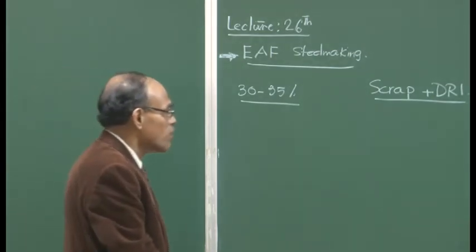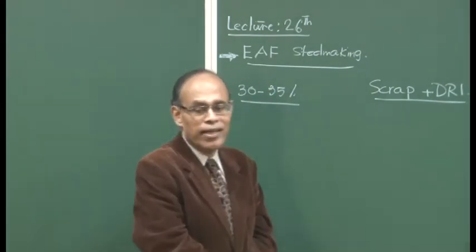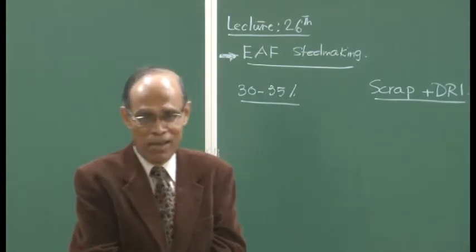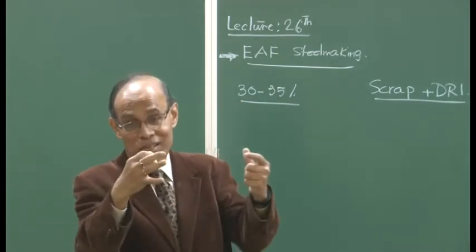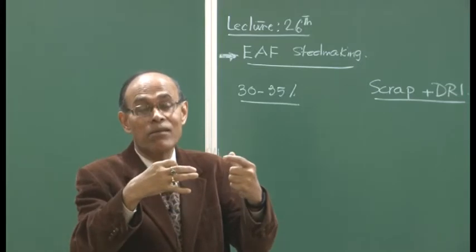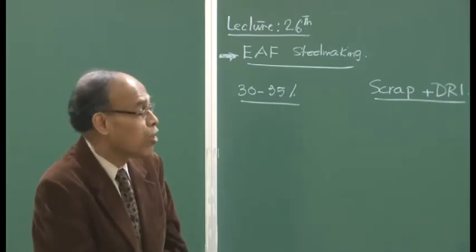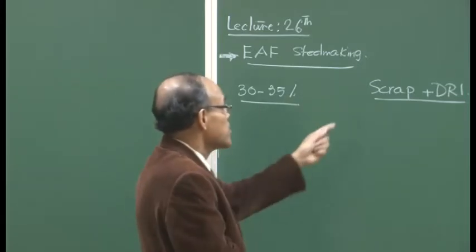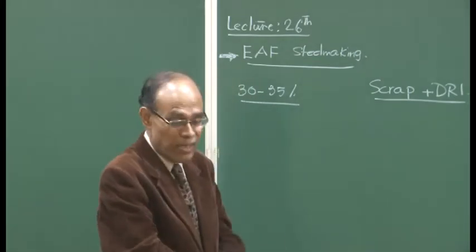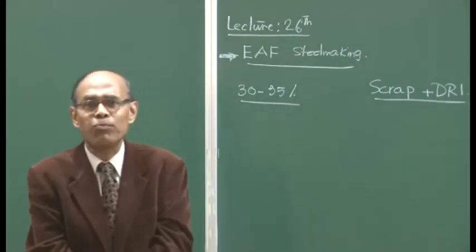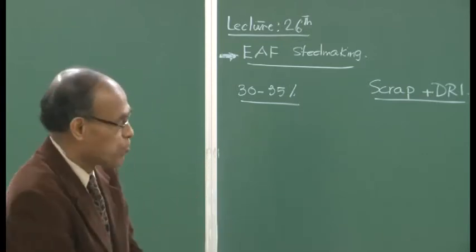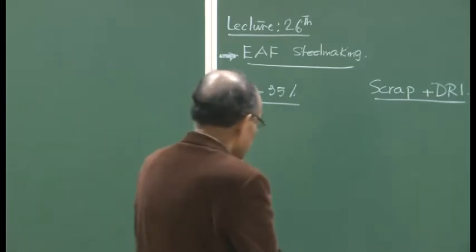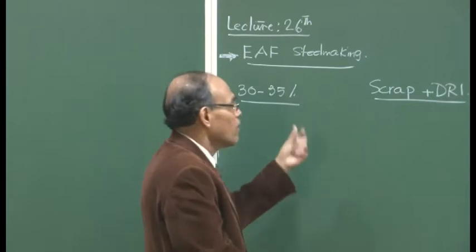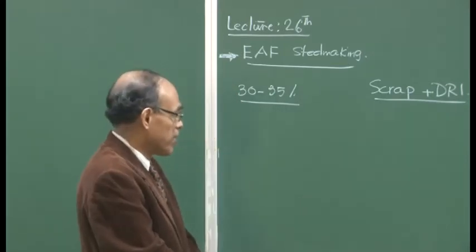You must understand here, if you are using scrap, in that case very little refining is needed, unless your selection of basic scrap is faulty and you have gotten all kinds of contamination in the scrap, then of course some refining is necessary. But if you can sort the scraps properly in the scrap sort yard of an electric arc furnace plant, very little or no refining would be necessary in the steel making process.